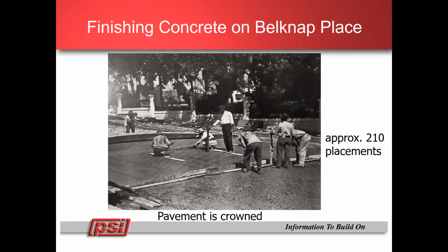What was interesting, because the shaping of the subgrade was so difficult and the specifications required the crown of the road to be approximately 6.5 inches thick and the shoulders at the curb to come down to 4.5 inches, the street pavement was actually shaped. The subgrade was held level and the concrete was placed with formwork to create this crown effect. And then the gentleman in this picture finished it, and I'll describe later the finishing process. Based upon the approximate number of joints that were counted on the road in this picture, Belknap Place was placed in approximately 210 independent concrete placements.